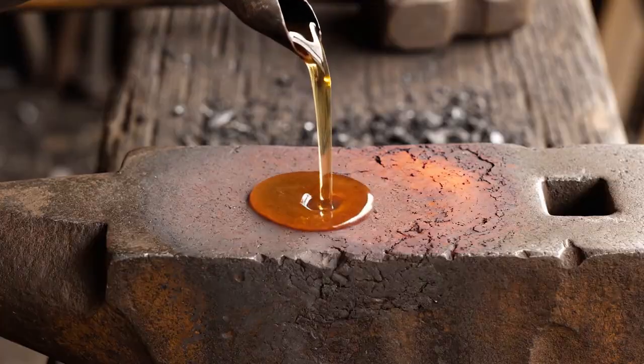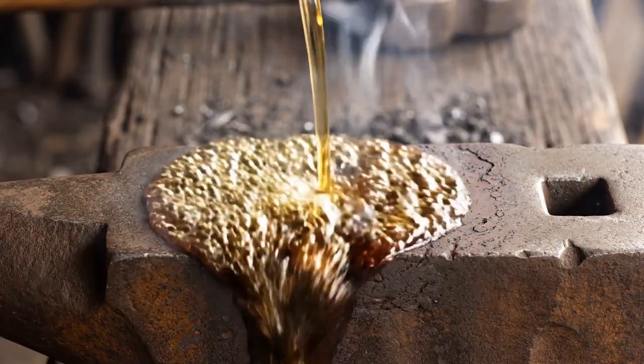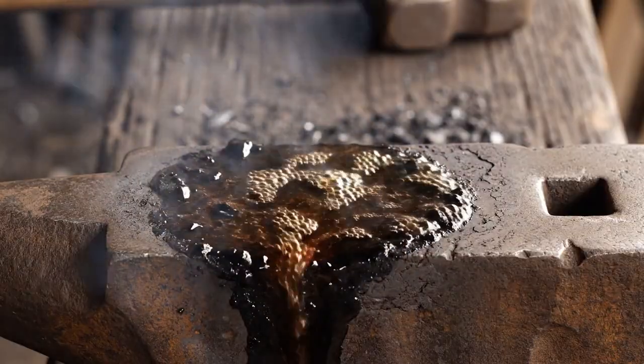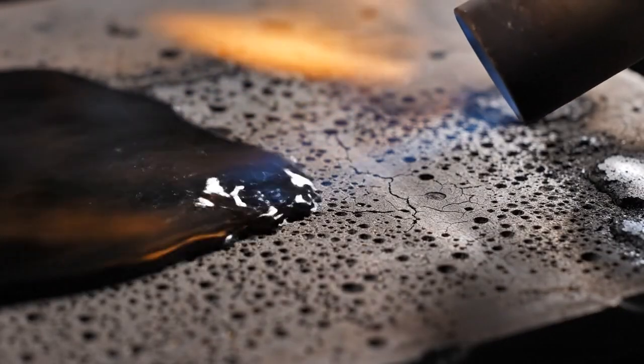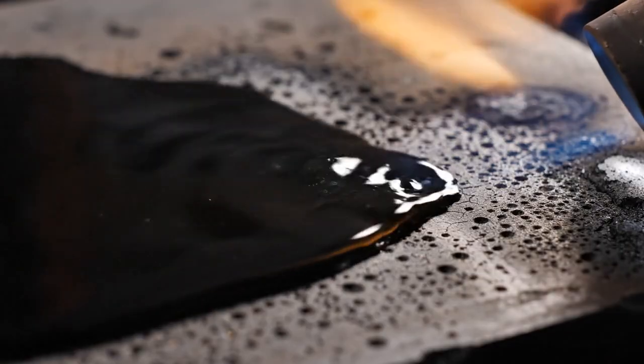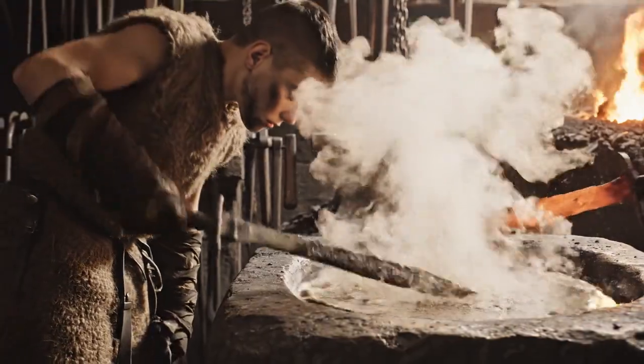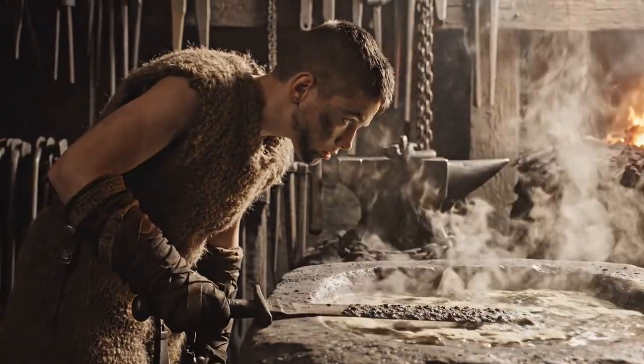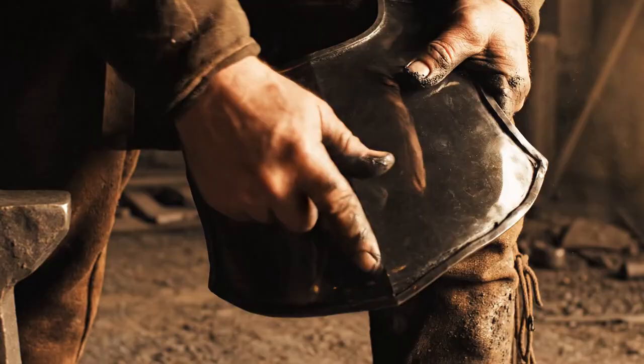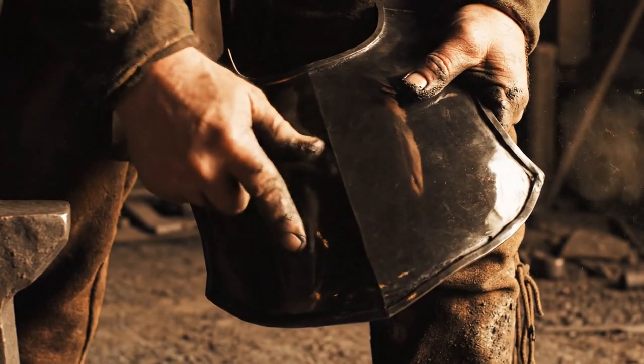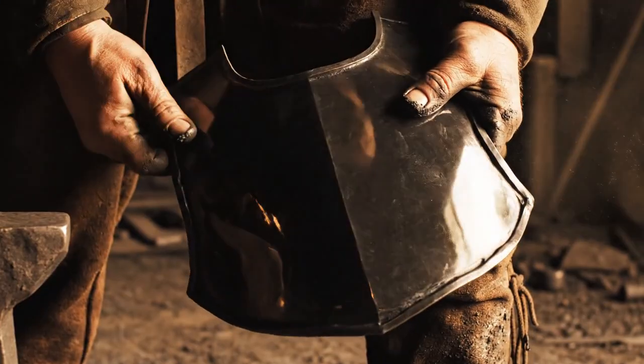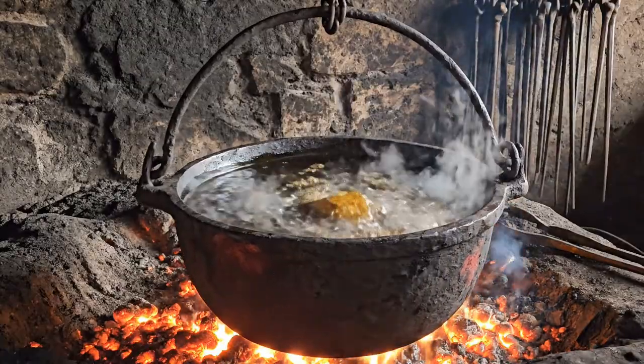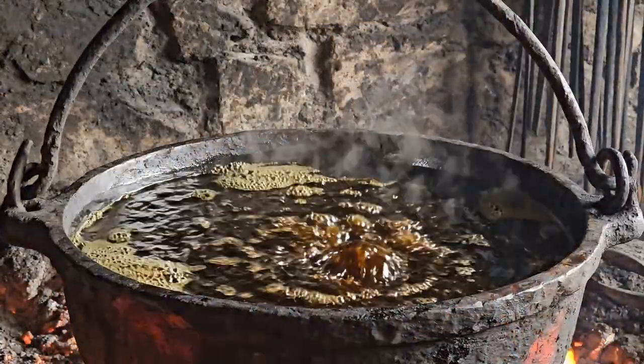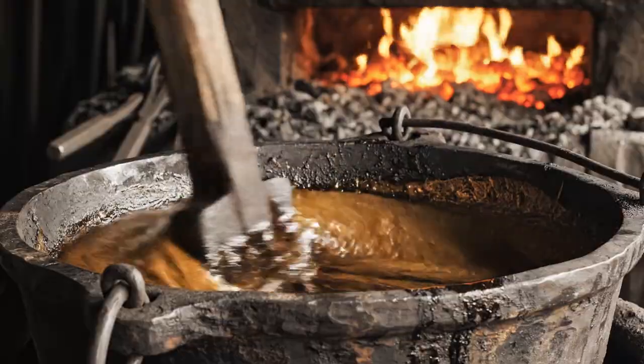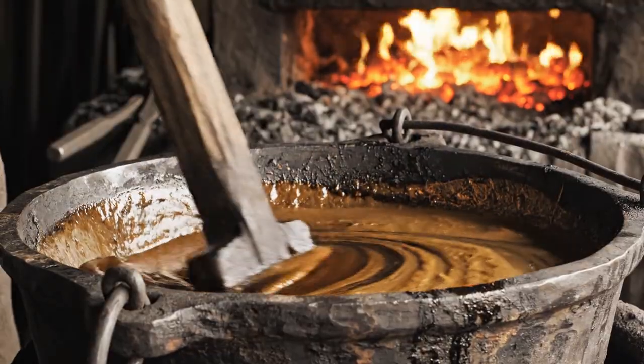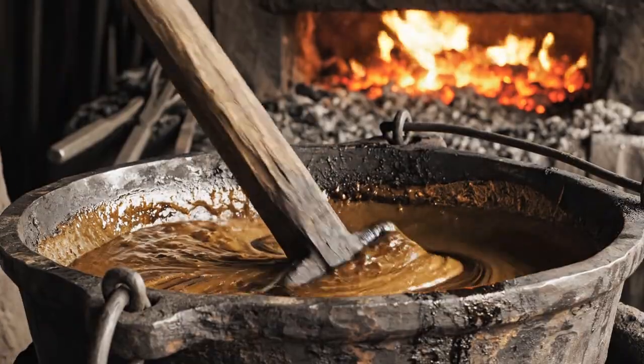What they did not know, and what modern chemistry has confirmed, is that heat dramatically accelerates the polymerization process. At room temperature, raw linseed oil can take weeks or even months to complete its cure. At 200 degrees Celsius, cross-linking begins almost immediately. The result is a thin, tough film that fills every microscopic pore and irregularity in the magnetite layer beneath it. The oil penetrates spaces that the oxide cannot seal on its own, and by solidifying into a polymer, it creates a second barrier of protection.